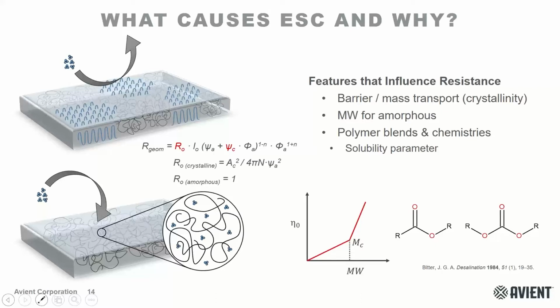And that's important because ultimately, when the disinfectant or the chemical reagent it's being treated with penetrates into the sample, it improves the mobility of the chains. And chain mobility is what allows these things to stress crack. And so for an amorphous material, what can you do? Let's say I have a transparent part, it needs to be transparent, I cannot add crystallinity. Well, molecular weight is probably the easiest lever to pull for an amorphous material.